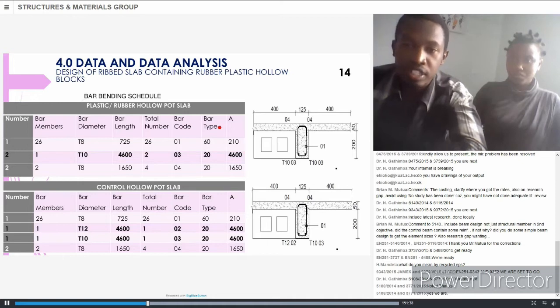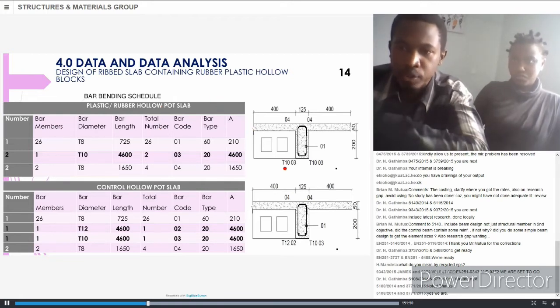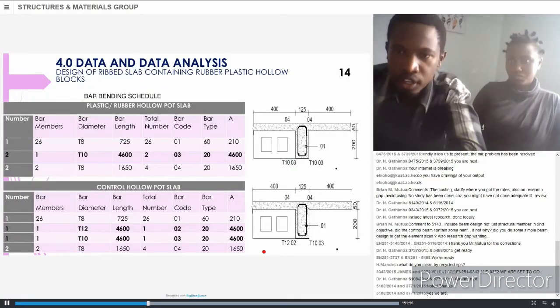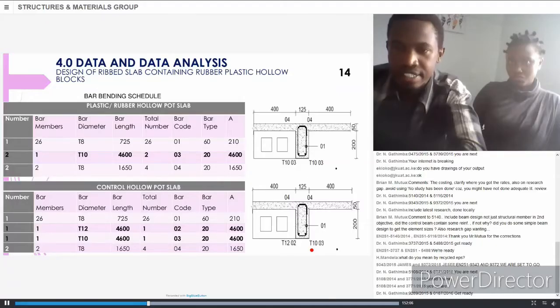So based on the unit weight, we did a design of a rib slab containing rubber plastic hollow block, and according to the area of steel required for the design of the rib slab, we found a difference to be at T10 on the rubber plastic hollow block and at T12 on the concrete hollow block. The difference is that there are 2 T10s at the bottom and 1 T12 and 1 T10 at the bottom of the concrete hollow block slab. So there's a saving on the material usage when you use a plastic rubber hollow block, which is lighter in weight. 1 minute remaining.